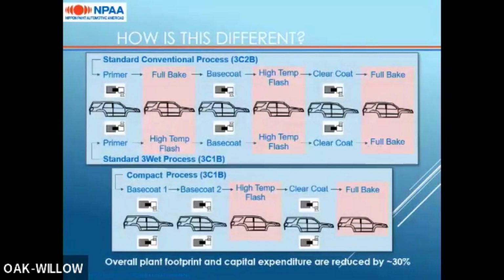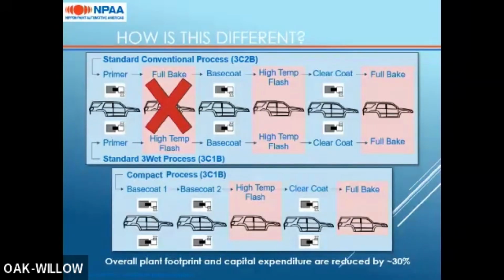So again, for standard conventional 3-coat 2-bake and traditional 3-wet processes, we still have the full bake or high temperature flash off oven between primer and base coat. Then high temperature flash off after base coat, clear coat, and then full bake after clear coat. With this process, we are able to eliminate that first oven after primer to give us the compact process of base 1, then base 2, high temperature flash off, clear coat with full bake. So overall, this allows for plant footprint and capital expenditure being reduced by up to 30%, depending on whether this is a new line being built or adaptation of an existing line.